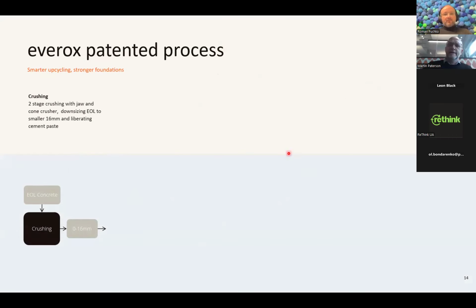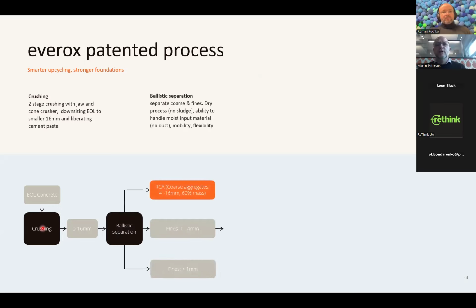So a little bit more in detail, how does our patented process work? We receive end-of-life concrete on site. We do crushing in 2 stages. The essence of the crushing is to keep the integrity of the primary materials. We don't want to destroy the stones. We want to more rub off the bond between the cement paste and the stone. Out of that crushing process, we get a 0 to 16 millimeter material, which goes into our ballistic separator.